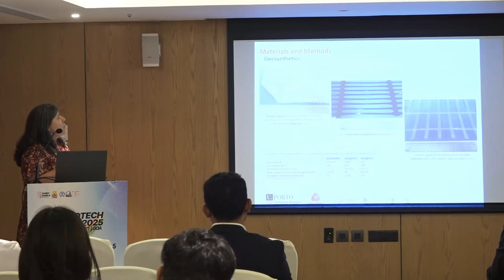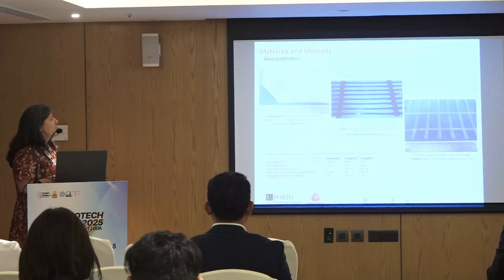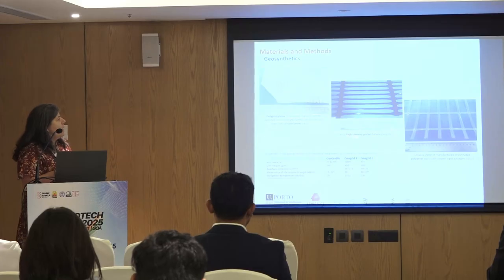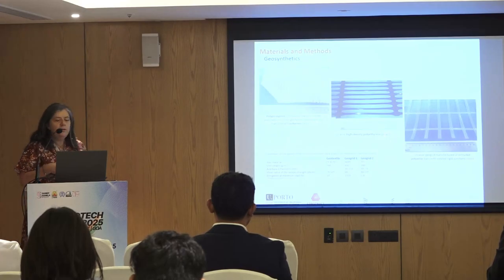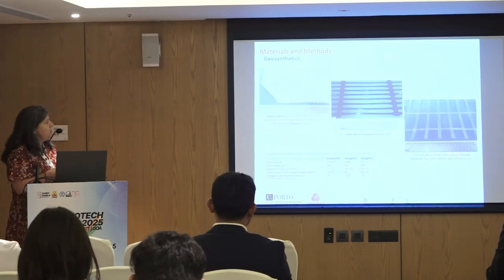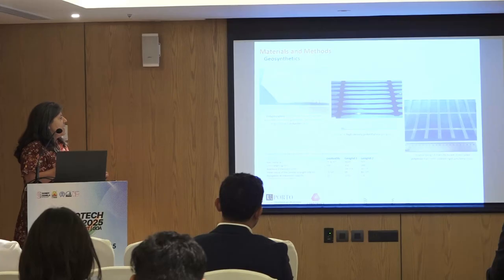Three geosynthetics were used: a geotextile, a polypropylene geotextile reinforced with high-strength polyester yarns, and two geogrids, one a high-density polyethylene geogrid, which we call GG1, and the other a uniaxial geogrid manufactured from polyester yarns, which we call GG2. The selection of these materials was made trying to have values of their tensile strength as similar as possible.